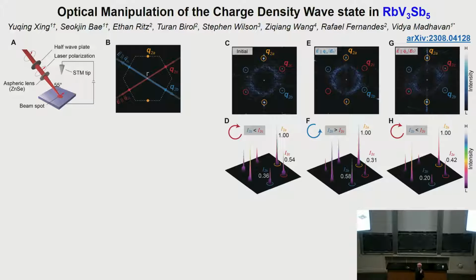The first one is without light. Without shining light, she observes what the Princeton group observed. There is a sense of handedness in the peaks of the CDW intensity. Now she can shine light along the weak direction. For example, this direction is weak. So she can shine the laser, retract the tip, put the beam in with the polarization along this direction, and then switch off the laser and push the STM tip down. Now the intensity is reversed, or the sense of chirality is reversed. Then she can go back and put the polarization along the now weaker direction, and she'll flip the chirality again.